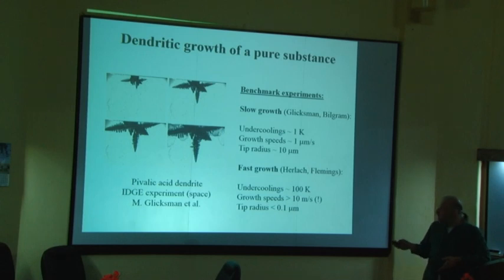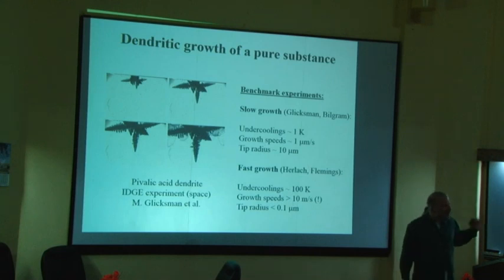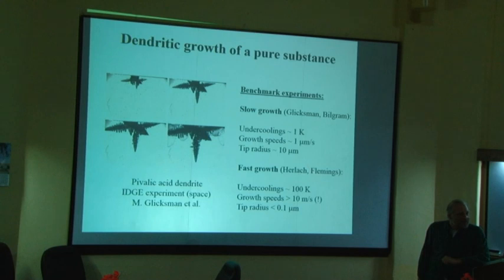Well, that means that you will develop temperature differences between the vicinity of the crystal and the far away fluid. And when you say temperature differences, you say in reality there is a very slight density difference, and this will trigger convection. And so if you want to be in this limit that I have considered, where only diffusion is important, well, you have to take away convection.